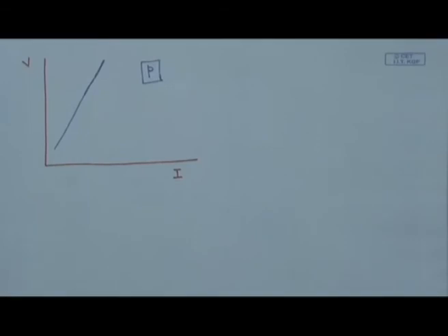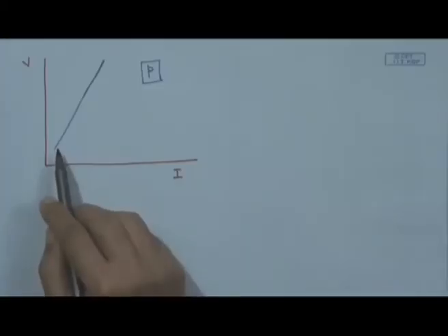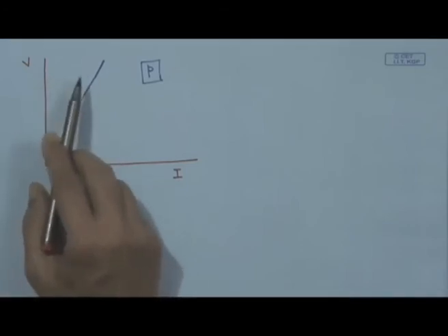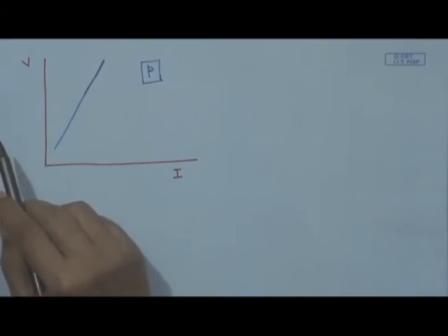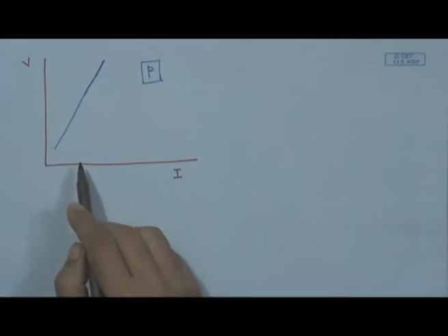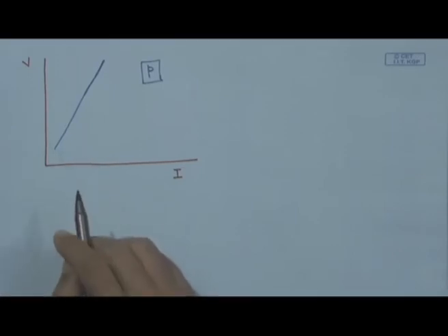Now, it is a planar DC diode, very simple. Here we find that the rise of this curve is quite steep. Physically, it means that for a small value of current we have to go with a very large value of volts. It can be a few thousands of volts, a few kilovolts, and we cannot even get a high value of current.